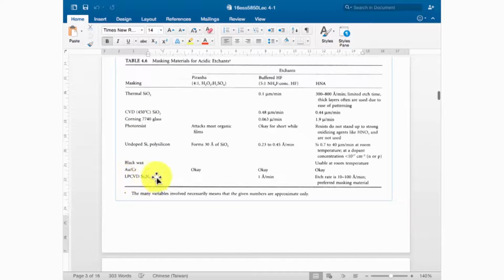So silicon dioxide and photoresist are not good. So the best one I think is LPCVD silicon nitride as a mask. Even though silicon nitride can be etched by the HF, hydrofluoric acid, it can still sustain for a little bit longer time. So I think so far silicon nitride is the best material to resist this kind of HNA etching system. Sometimes people use gold, okay, but gold does not have good adhesion to silicon substrate. So usually we will put chromium underneath. But consider chromium can be etched away by HF. So we need to put a very thin layer of chromium and a very thick layer of gold to maintain the mechanical integrity of the etching system.